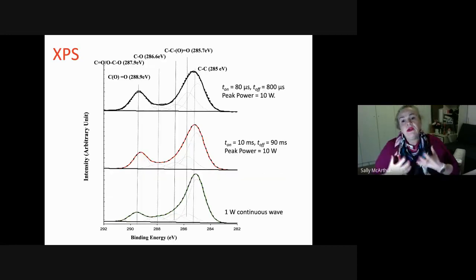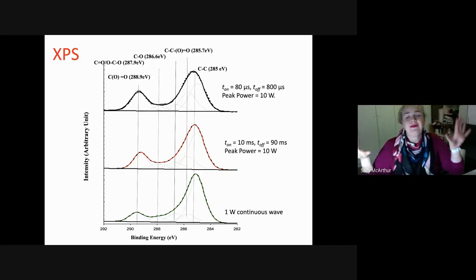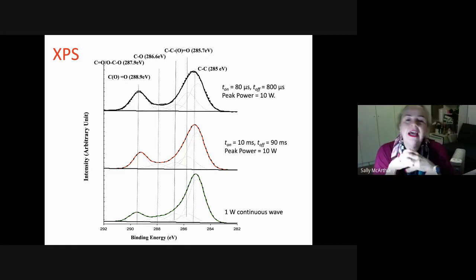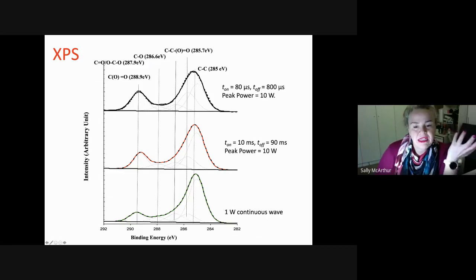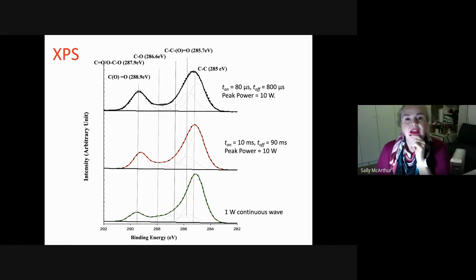And so if we look at the XPS, this is our first XPS profile for the talk, yay! We're looking at the different types of power distribution. This is the carbon 1s profile, so we're looking for those oxygen-containing species that are formed in the plasma. And you can see straight away that it's quite a complex oxygen-containing species.